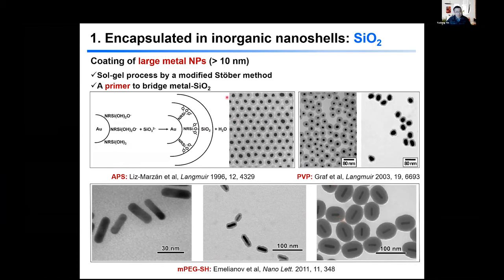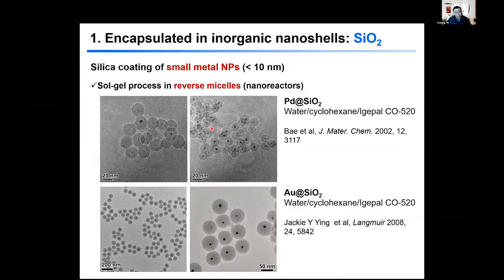But the challenge is that this kind of process is limited to large metal nanoparticles, typically larger than 10 nanometers, and that's because of complicated hydrolysis and condensation reactions when you try to coat smaller particles. So people moved the hydrolysis reactions to micelles, reverse micelles, so that we can coat really small nanoparticles with silica. In this case, usually people do a reduction reaction to produce these metal particles directly in these reverse micelles. They're actually called nanoreactors. The reaction is limited inside the micelles so that the particle size can be controlled. And the hydrolysis reaction of organosilane can also be introduced here, and then we can achieve very thin coating.